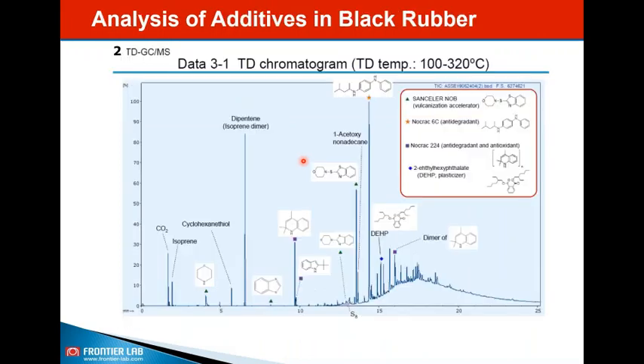Another common method is thermal desorption. Most people are interested in looking at the polymer as well as the additives in any polymeric material. Here is an example of black rubber, which is used in the tire industry. As you know, the additives are critical to tire performance because it has to have different combinations of vulcanizing agent, anti-degradant or antioxidant, and plasticizer. So the tire producer needs to know the nature of this material and the additives present. This can be accomplished by doing this thermal desorption with our PYGCMS.